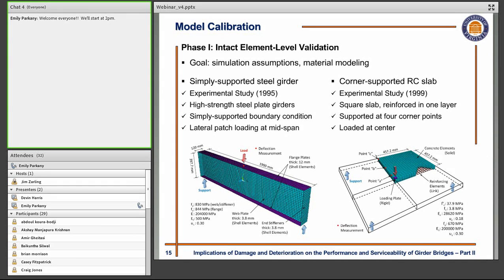All the material and geometric nonlinearities in this model we extracted from the test report according to their tested specimen. On the other side, for the next specimen, we selected an experimental study performed by McNeice back in 1999 on a corner-supported 2-way reinforced concrete slab. This is actually the basis of the numerical analysis of reinforced concrete structures in deck applications. In order to take advantage of the symmetry in loading and geometry of the structure, we simulated only 1/4 of the slab in our study. Again, similar to the steel plate girder, all the geometrical properties and material characteristics we extracted from the test reports.